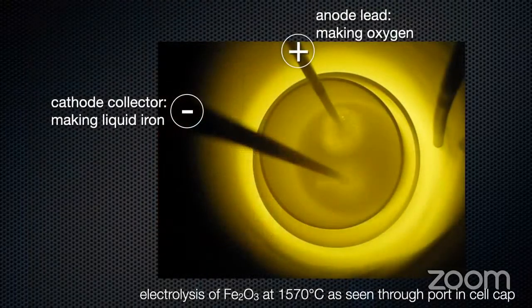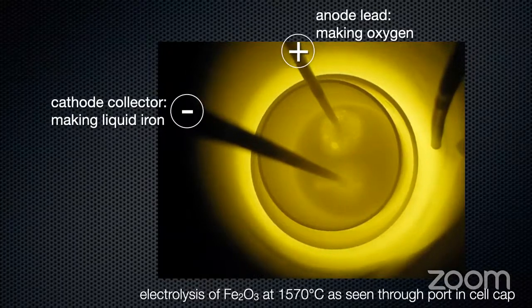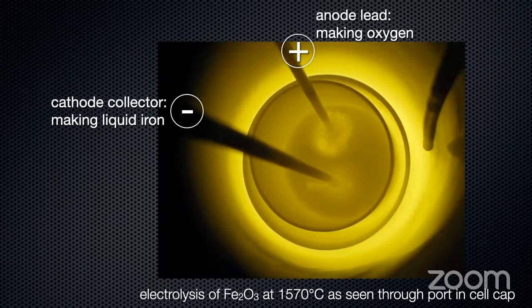And now this is some visuals. This is looking down through the cap. And over here, this is the anode. In the early days, we were using platinum group metals. You'll see the thing bubbling off oxygen here. And this is a molybdenum plate, vertically disposed. Iron is forming on the molybdenum plate and dribbling down to the bottom. And this is a silicate, molten silicate. So this has got some viscosity, but you'll see there's enough fluidity that you can see things happening. You can see the bubbles coming off the anode. And this is the beginning.